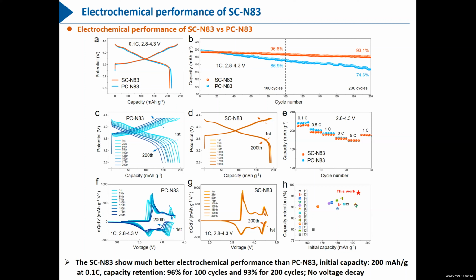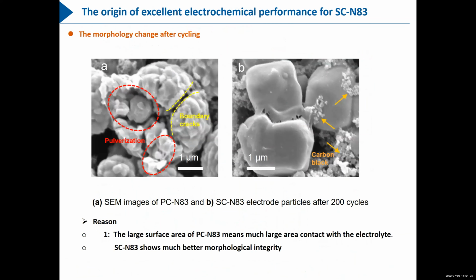So why? There may be some reasons for the good performance, so we tried to study these materials. First, we did some morphology study after cycling. This is polycrystalline and this is single crystalline, right? You'll find that the polycrystalline material, after 200 cycles, has boundary cracks and also pulverization. For sure, that's because the polycrystalline material has a very large surface area, so there is much more contact with the electrolyte. But the single crystal has a huge advantage: it shows much better morphological integrity.